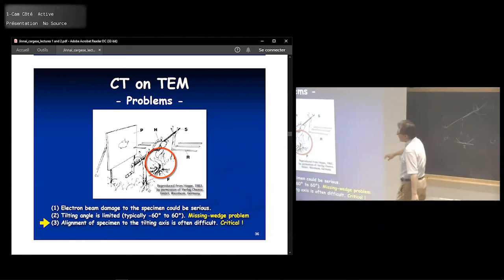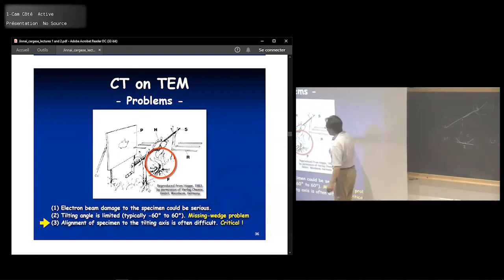Okay, anyway, summarizing, what we are doing is that we have a sample, and then we rotate the sample in the TEM, take projections, and then using these projections, we can reconstruct the data. For doing this CT in a TEM,